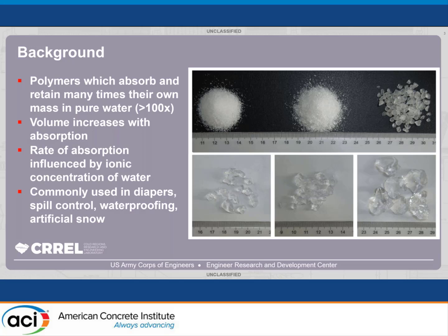So then a little background on these superabsorbent polymers, also known as SAP. They absorb many times their own mass in pure water. It can be over 100 times. And the image here shows that as more water is introduced to the SAP, it's able to grow a lot larger. These things are commonly used in diapers, spill control, waterproofing, and maybe it's even something you've seen before. And the amount that is absorbed is highly influenced by the ionic concentration of the water that it's in. So if you have fresh water compared to salt water or the water in concrete, it's going to have a very different absorption rate.